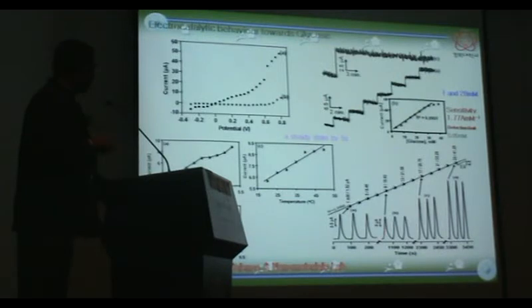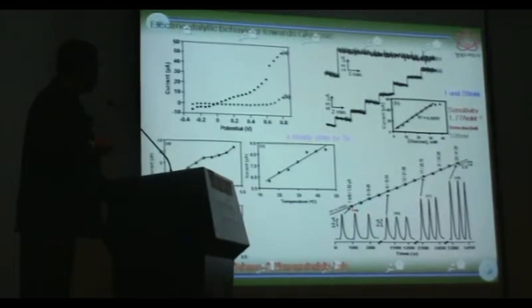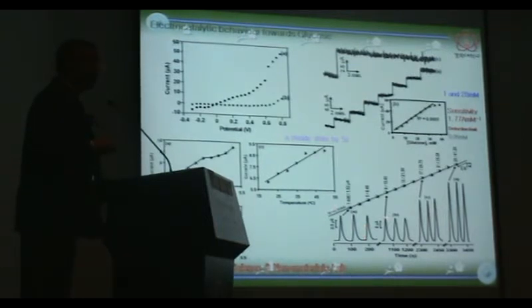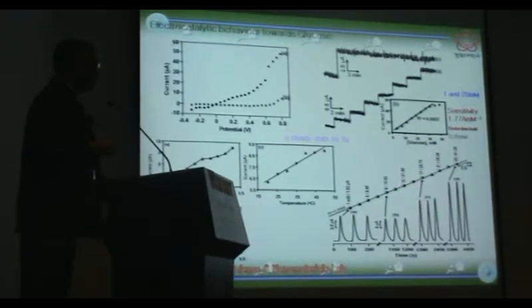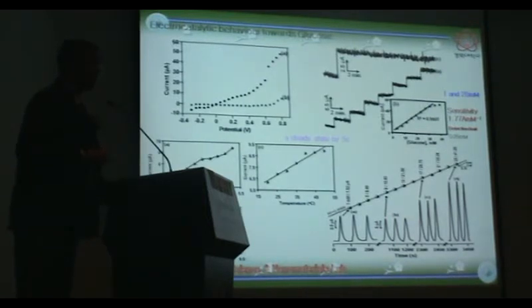This is the flow injection amperogram of the sensor electrode, and the current values are very near to each other. That shows the reproducibility when the same concentration of glucose was injected. And when we increase the concentration of glucose, the current value increases. So it shows high reproducibility and high stability, and shows linear variations with the concentration. Okay, so this electrode is ideally suited for analyzing glucose in the flowing stream.